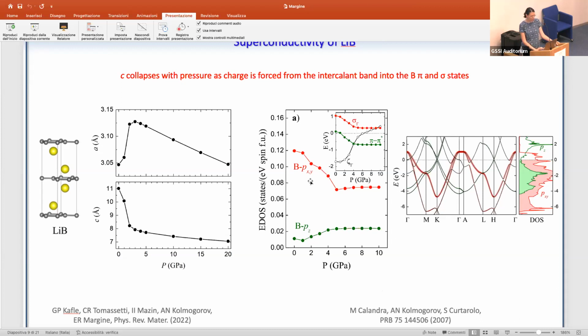And indeed, if you apply pressure, you see that there is a large variation in the density of states from both boron pi and sigma states up to about 5 gigapascal, after which there is almost no change in the DOS. And this change in the electronic structure is directly related to the change in the crystal structure of lithium boride. At low pressure, the lithium-lithium interlayer distance collapses rapidly, and the charge from the lithium band is forced into the boron sigma and pi states. Once this redistribution is complete, there is almost no change in the density of states at the Fermi level.